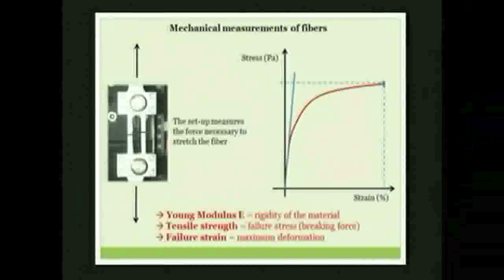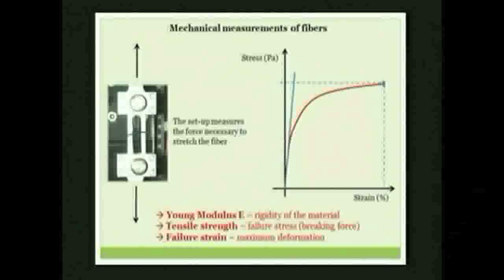Then after, you have the plastic regime here. Here, at this point, the deformation is completely irreversible, okay? And here you have the failure stress, the maximum breaking force that the material can stand. Corresponding to this value, which is what is called the tensile strength, you have the failure strain, which is, as you can easily understand, the maximum strain deformation that the fiber can stand also. Okay? These three, Young modulus, tensile strength, and failure strain, are the main mechanical features that you want to get when you make a tensile load experiment on your material. And it characterizes the mechanics of your material.